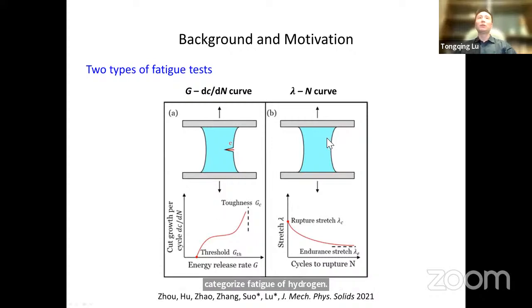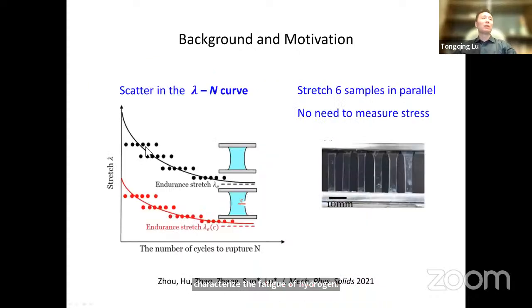The other type is we apply cyclic load to a sample without precut. We apply a stretch amplitude and record the number of cycles to rupture. So this is called the lambda-N curve. This is another type. And in this work, I collaborated with Zhigang. We use this type of fatigue test to characterize the fatigue of hydrogels. For the lambda-N curve, actually there's a feature in this curve. For a given stretch amplitude, usually the number of cycles to rupture will differ from sample to sample. That means that there's a wide scatter in such curves. If you are familiar with the fatigue test, it's a common phenomenon.